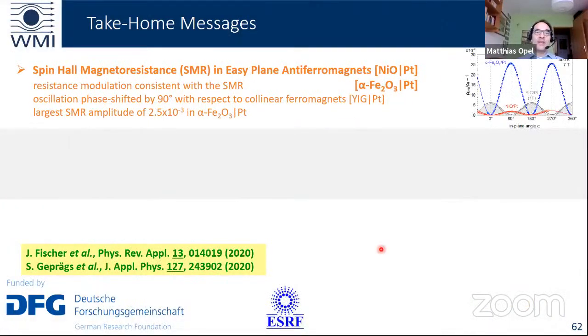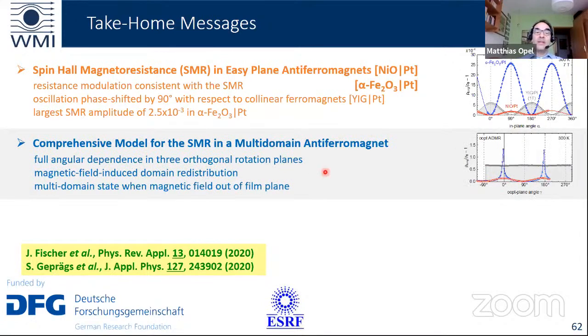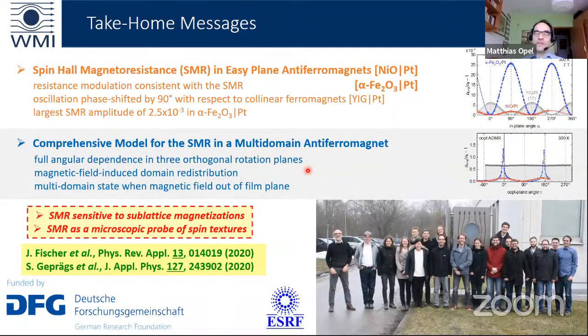I showed you the spin Hall magnetoresistance in easy plane antiferromagnets, nickel oxide platinum and hematite platinum. I showed you that we found a resistance modulation consistent with the SMR and an oscillation which is phase shifted by 90 degrees with respect to the collinear ferromagnets. And we found a very large SMR amplitude of 2.5 times 10 to the minus 3. We developed a comprehensive model for the SMR in the multi-domain antiferromagnets. We showed the full angular dependence in 3 orthogonal rotation planes, found a magnetic field-induced domain redistribution and a multi-domain state whenever the magnetic field is pointing out of plane.